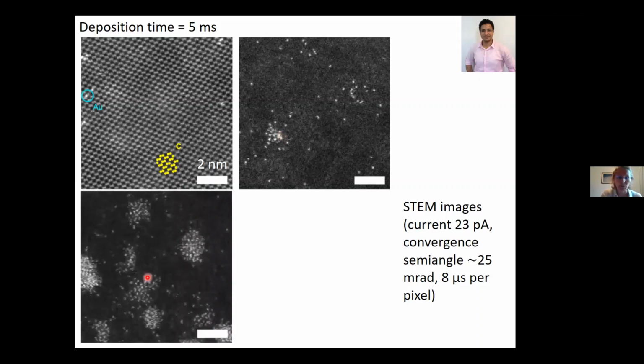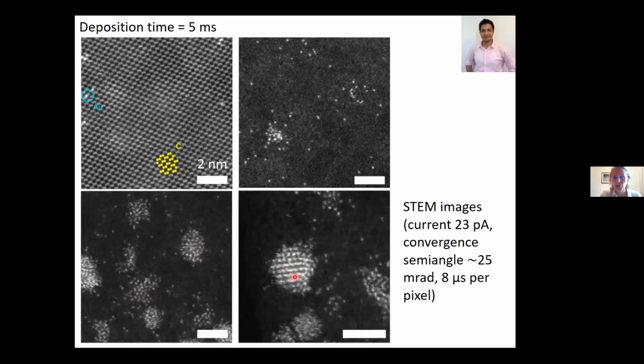And this is another example of these atoms here. But as I said, please remember, you're not looking at a 2-dimensional image. This has a 3-dimensionality to it. And then obviously here we also see, after 5 milliseconds, a nanoparticle. Now, this is one of the issues with TEM and anybody reporting microscopy images, is you get so many structures on the surface.